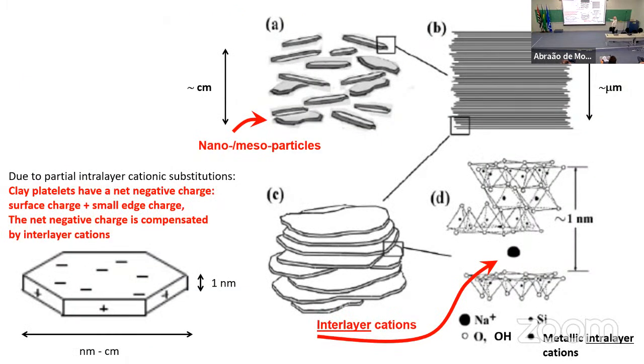When you look at this closely, clay particles are typically decks of nano cards. Each of these cards is a single crystal, one nanometer thick. The dimensions in the other directions can vary from one clay type to another. What distinguishes the different types of clay is what kind of metals you have in the middle part, because there are tetrahedra and octahedra, and in the middle of the octahedra there are some metals sitting. What kind of metal is sitting here gives the name to the clay. By stacking these cards on top of one another, you get these particles, and from those particles, you get macroscopic behaviors.